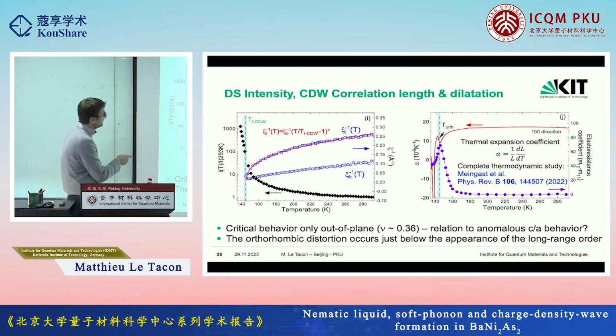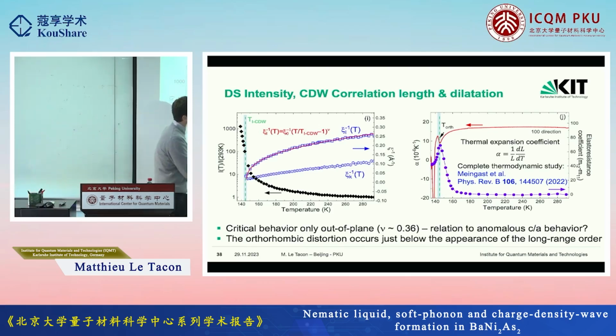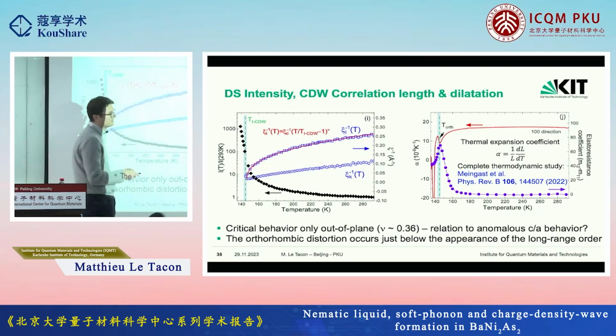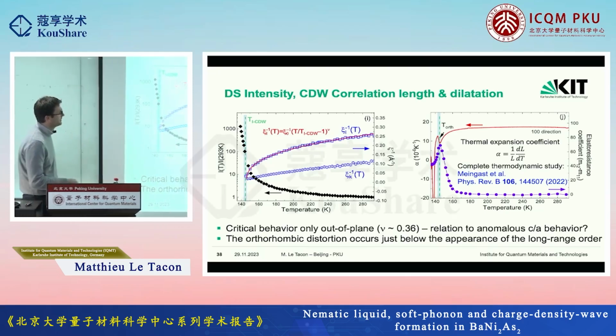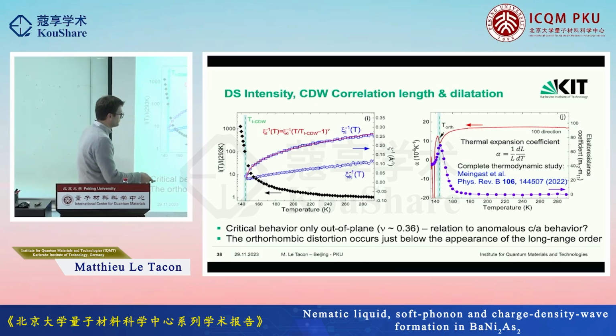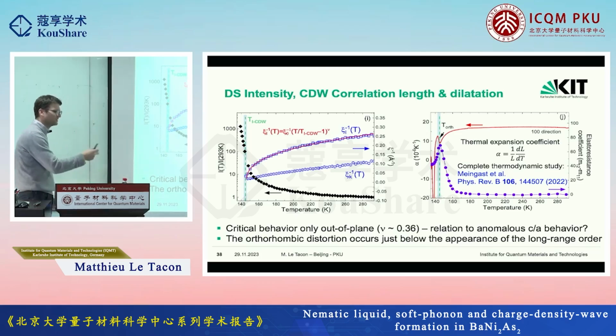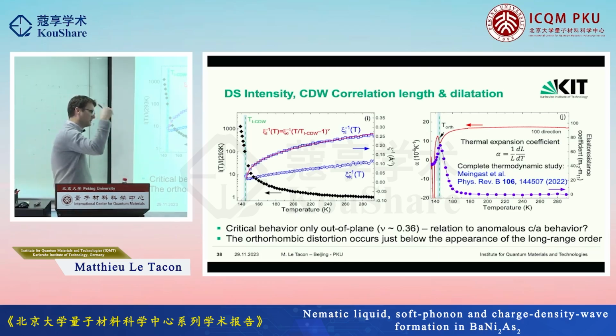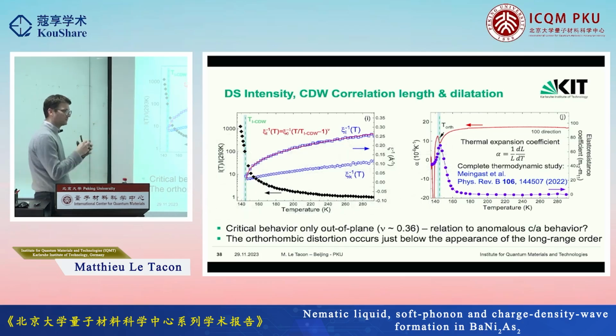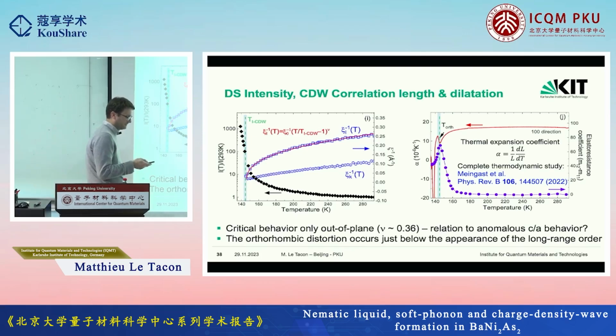And you can compare this transition temperature with the thermal expansion coefficient or with the elastoresistivity, for instance. And you can nicely find where the CDW long-range order takes place and how it compares with the orthorhombic distortion. Long story short, the orthorhombic distortion occurs just below that temperature, within 1 or 2 Kelvin. So you have the condensation of the charge-density wave, the long-range order that forms, and then you have this tiny orthorhombic distortion that forms.